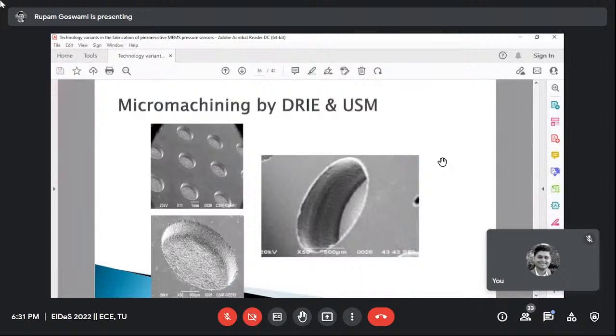So here on the left side, you can see the two pictures. One is the array of cavities, and one is the enlargement of one of the cavities, made by ultrasonic machining process. And you can see that the finishing of the walls is not that good as in the case of DRIE, which we see here. But if it is followed by some laser kind of finishing touches on the edges, it is improved. But we have made the device and it worked very well.